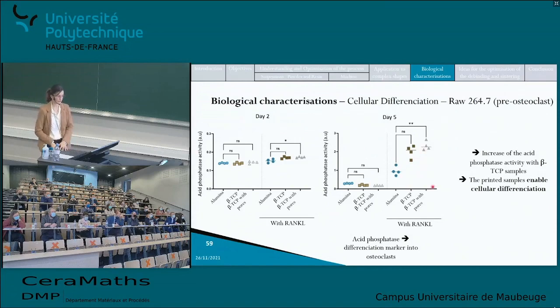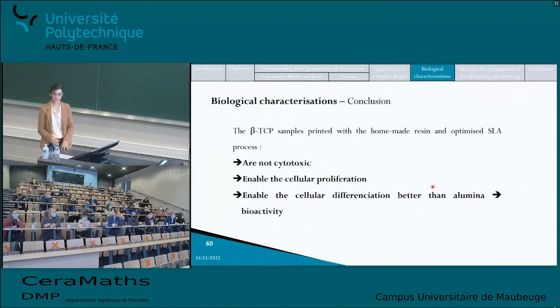So in conclusion, the β-TCP samples printed with the homemade resin and the optimized SLA process were not cytotoxic. They enable the cellular proliferation, and they also enable the cellular differentiation better than the alumina samples, which confirms the bioactive properties of the β-TCP, because the alumina is bioinert, so it doesn't enable the cellular differentiation, whereas the β-TCP samples enable the cellular differentiation.